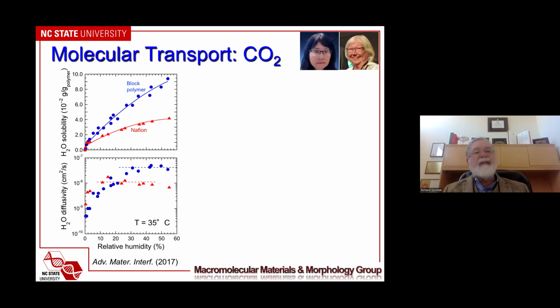So, getting back to that block polymer that I showed you just a few moments ago. Here are results showing the water solubility and diffusivity as functions of the relative humidity. So this is the humidity of the feed in which we are incorporating CO2 or nitrogen. And you see that the water solubility is much higher in this material than Nafion. In fact, this material has a higher transmission of water than Nafion does. And its diffusivity is higher at high relative humidities.